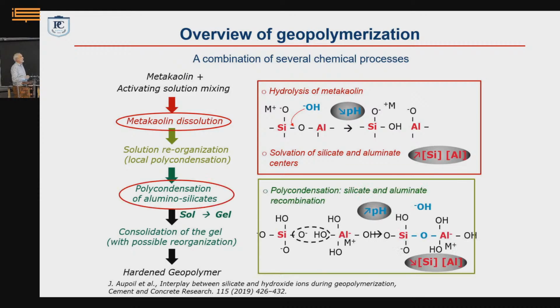But once the silicate and the aluminate ions are released in solution, they recondense to form the solid, being a glass, a hydrated glass, a gel, or a so-called geopolymer, but this condensation releases the hydroxide ions. So in a sense, this is catalyzed by the hydroxides. Okay, the water here is not really a reactant. It's just a source of OH minus to dissolve the system and allow further precipitation, of course, of the aluminates and of the silicates. Okay?